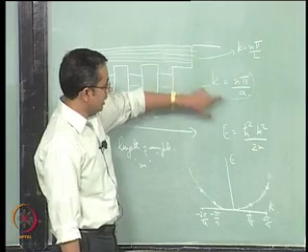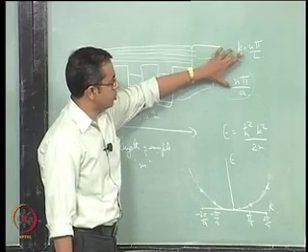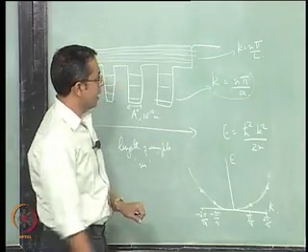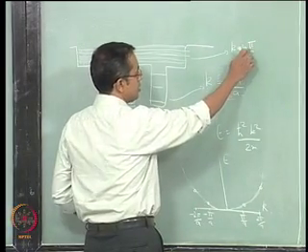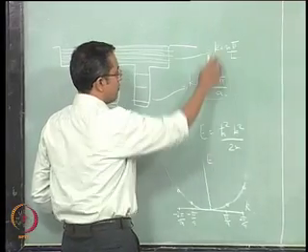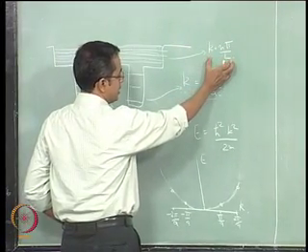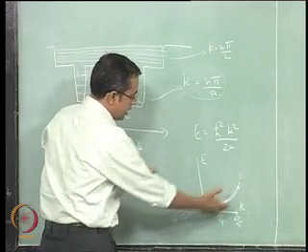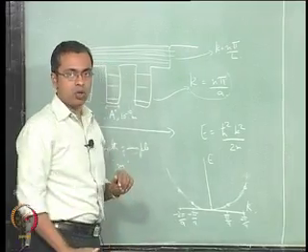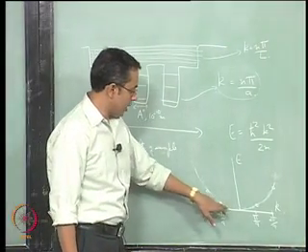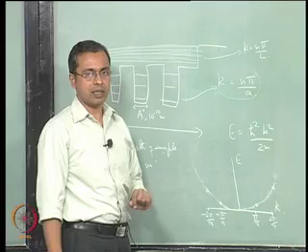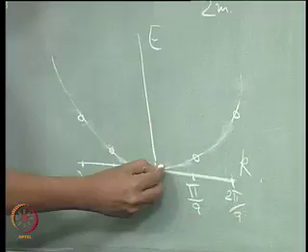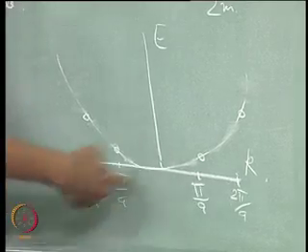The point you have to understand is the difference between these two levels of confinement. This is n pi by a, so n pi by a shows up here. I said that L is a very large number, so the phenomenon is still true once you confine it to a distance L. Exactly the same thing holds: a continuous parabola is no longer permitted, and only specific points along that parabola are allowed. The only difference is that since L is very large, those specific points are very close.